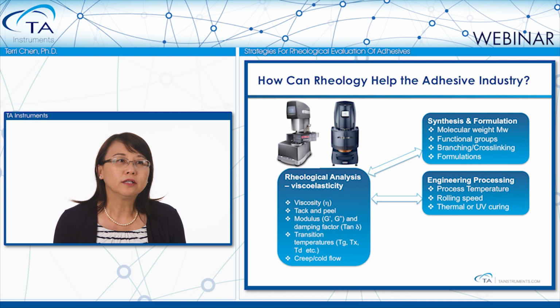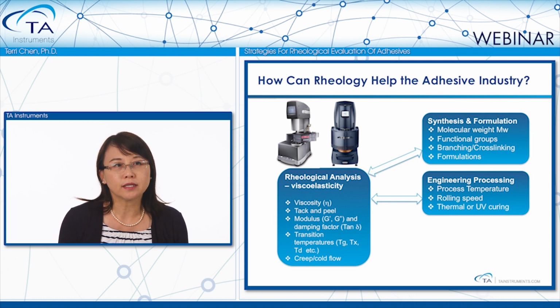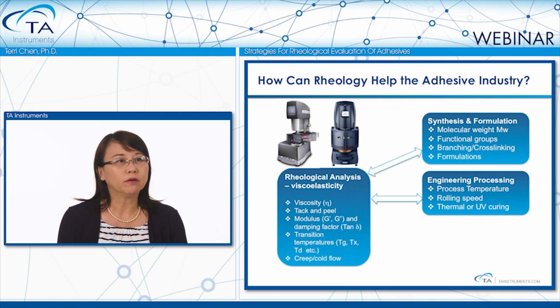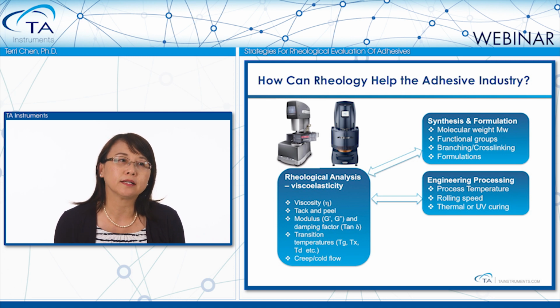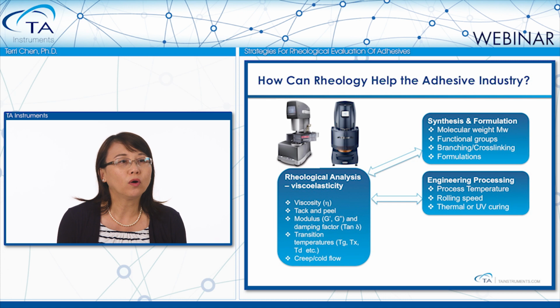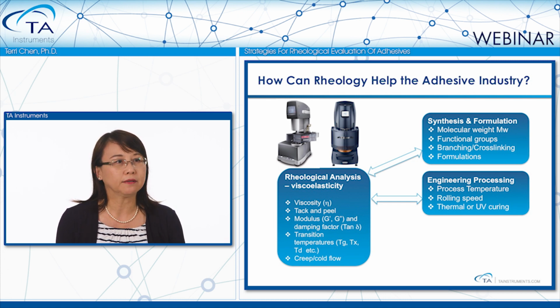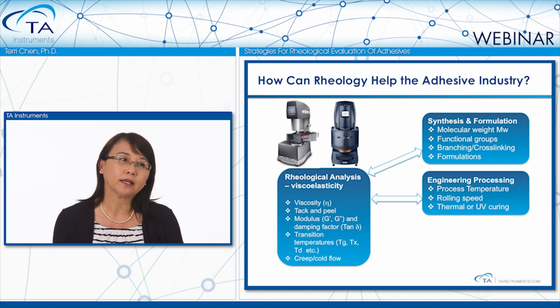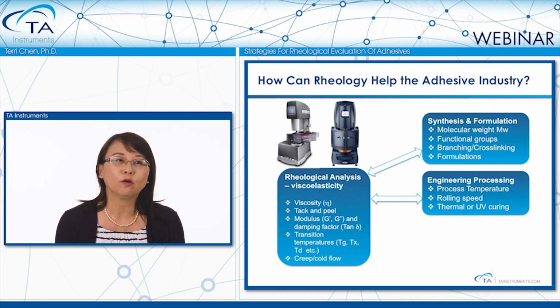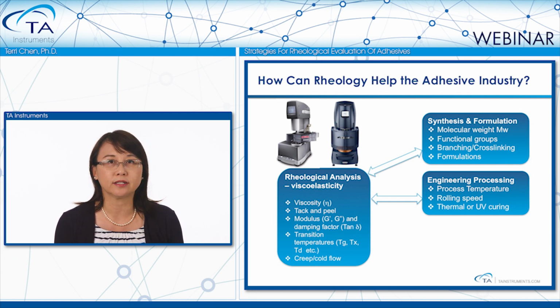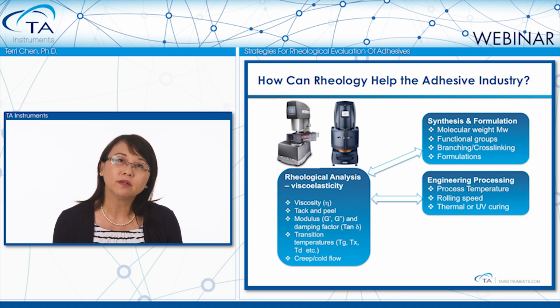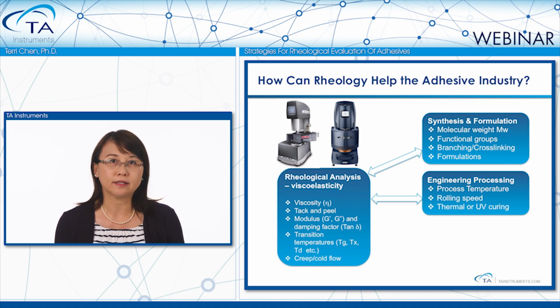Second, rheology tests can also help to guide processing conditions. For example, in adhesive coating process, rheology measures shear viscosity of adhesive solutions or how it melts. It helps to guide the application's rolling speed. In adhesive curing, rheology test results can help to optimize the curing conditions, such as temperature, humidity, or UV intensity.